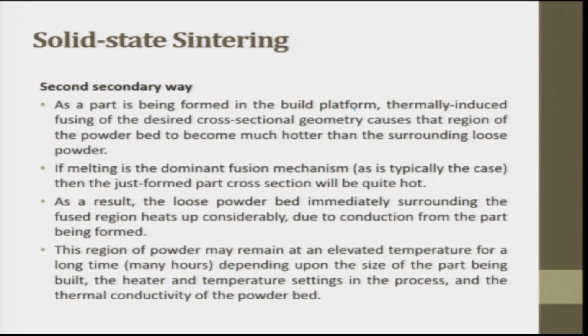As the part is being formed on the build platform, thermally induced fusion of the desired cross-section geometry causes that region of the powder bed to become much hotter than the surrounding loose powder at the cross section, right. If melting is the dominant fusion mechanism, then the just formed part cross section will be quite hot when you are doing selective laser melting. As a result, the loose powder bed immediately surrounding the fusion region heats up considerably due to conduction from the part being formed. This region of powder may remain at an elevated temperature for a longer time depending upon the size of the part being built, the heater and the temperature setting in the process, and thermal conductivity of the powder bed. So this part and this part are important.